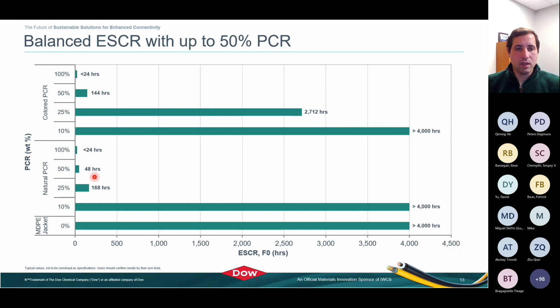You could find some applicability with PCR loaded at those amounts. One thing that's interesting and hypothesized around the colored in terms of performance is that you actually have more of a variety of polymer material and different sources, different molecular weights, distributions, things like that. You actually see a little bit better ESCR on the colored in this case versus the natural, whereas previously we saw the opposite.